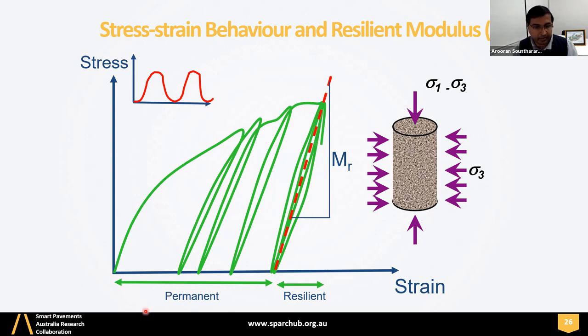So this permanent deformation is typically, in terms of distress mechanisms, the mode zero rutting, right? This permanent deformation is anyway expected even in the laboratory test, regardless of your compaction procedure. Even if you come back to the maximum density, the particles will still try to reorganize to their maximum stability. So it is typically mode zero rutting identified in the field. In the laboratory, depending on your loads and the initial compaction stage, the void ratio and density, the magnitude of the permanent deformation will change.